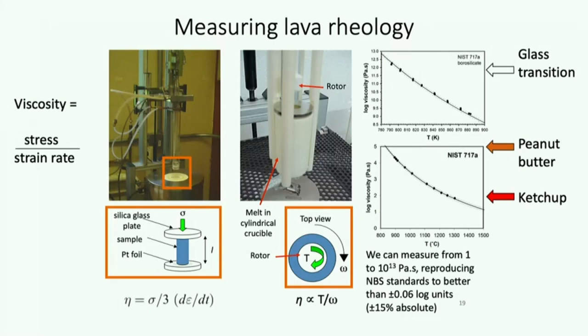Anyway, basically we have a spindle that goes into a cylindrical crucible. The spindle spins around and it has to work harder to spin at a certain rate if the fluid is more viscous, more sticky. And so here what you measure is the torque and the angular velocity, which translate to stress and strain rate, and viscosity is stress divided by strain rate. Hence its units are pascal seconds, because the units of strain rate, remember, are per second. So this one works well for viscosities in, let's say, the ketchup to peanut butter range, around 100 to 100,000 pascal seconds.